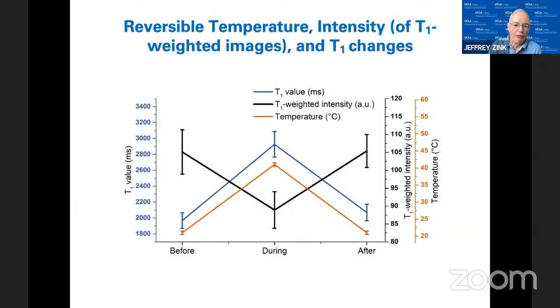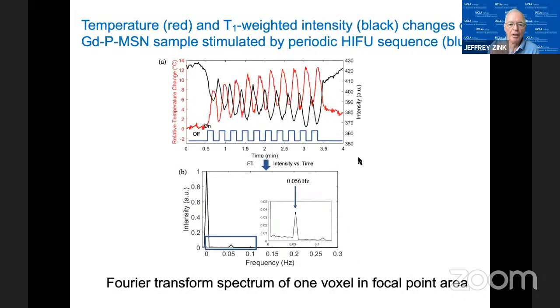We showed that, using the MRI to get these values, we can actually change the value of T1. Simultaneously, the MRI can measure the temperature. I didn't mention that, so we can actually measure the exact temperature at that focal spot. The temperature rises and decreases, as shown on the right. And the overall intensity that we see in the MRI image is shown in the bold black on there. So we can actually modulate it. What we do here is turn the HIFU on and off. We get this modulated T1 signal. And then the Fourier transform of that signal gives rise to a signal that is essentially amplified.